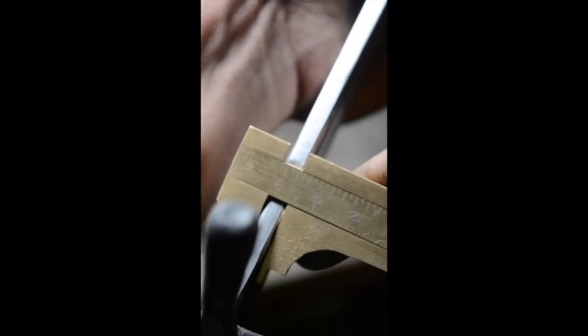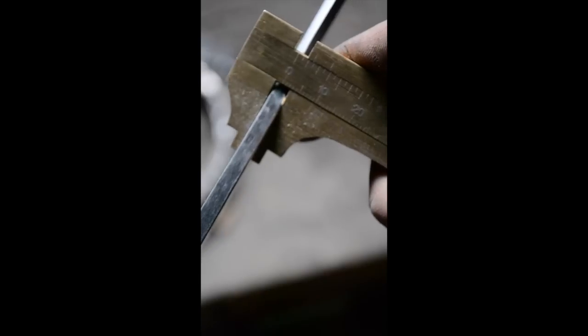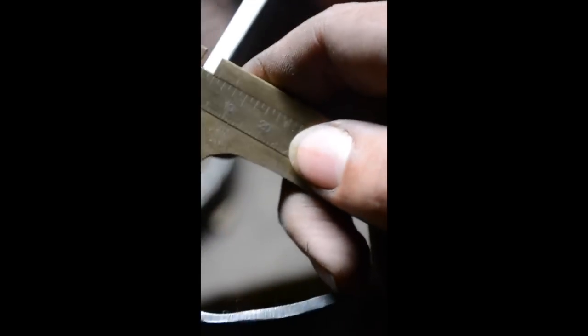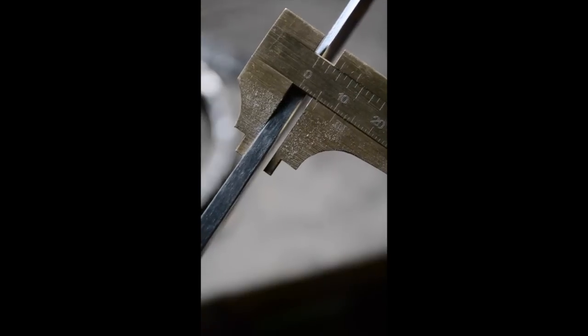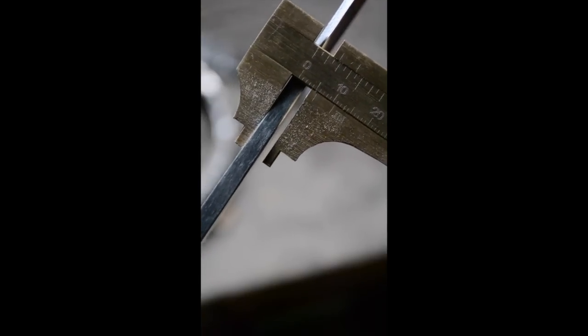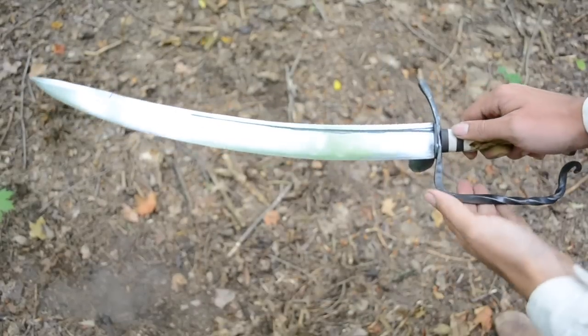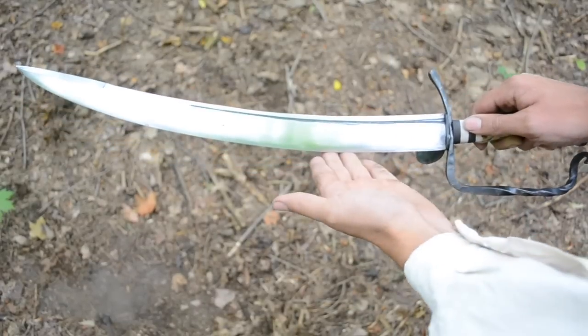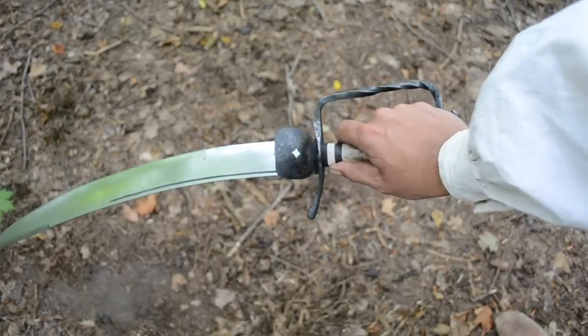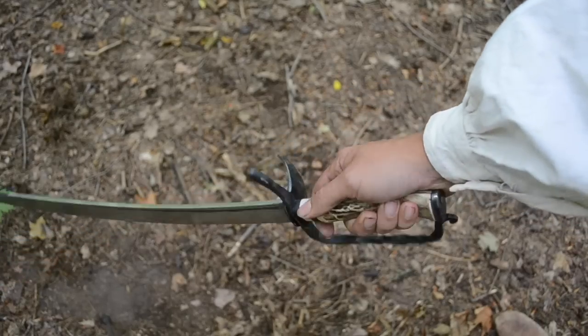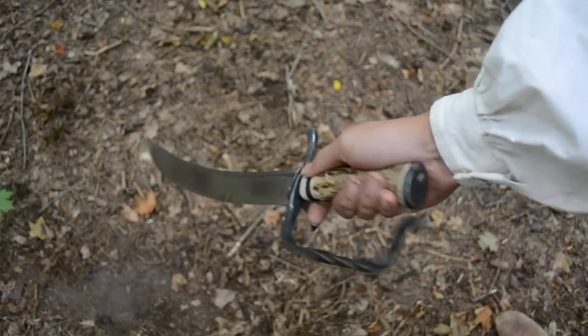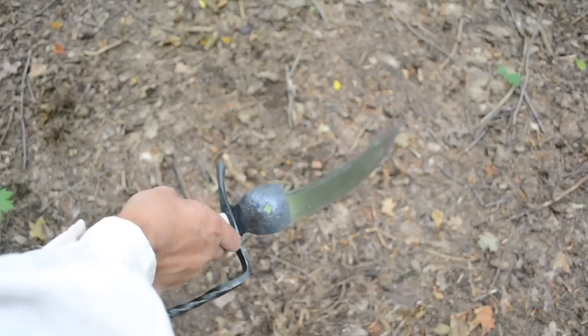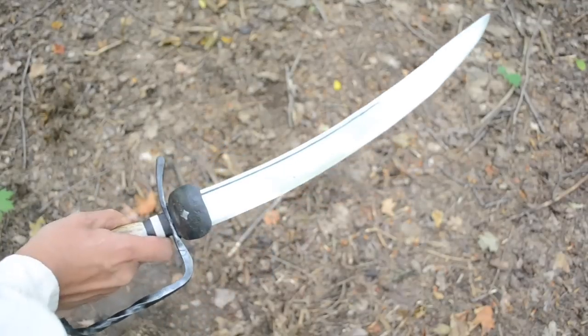After the grinding, the sword is 6 mm at the ricasso and 4 mm just below the false edge. This represents a decrease of about 30% along the sword's length, which is about what you want for a cutting sword. Here we see the finished product. It looks quite nice, I think you will agree. The only issue is that I screwed up one of the fullers, which is kind of messy. Whatever, it adds character. The final weight is a little over 2¼ pounds.